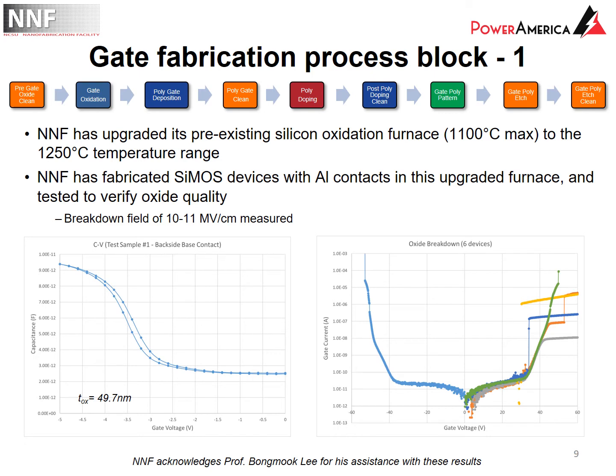So we did that with a silicon wafer. We loaded up a silicon wafer, oxidized it, and fabricated a silicon MOS, a silicon metal oxide semiconductor device with aluminum contacts, and we wanted to verify oxide quality. We were looking to make sure that we were able to get the oxide thickness that we wanted, as well as the breakdown voltage, and we were able to successfully do that with both of them.